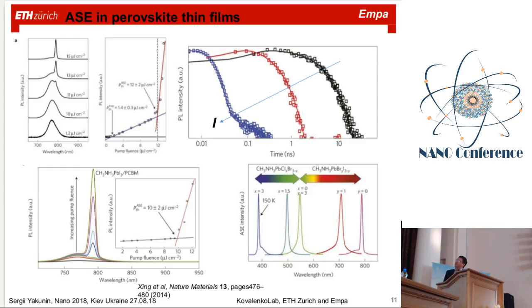In perovskite, these optical gain effects start, in principle, at quite a low threshold, which shows very great potential of this material for laser application. And another very cool ability of this material is that you can almost continuously tune, so actually not almost, but really continuously tune through the whole visible range, just playing with halide composition, as I told in the previous slide.